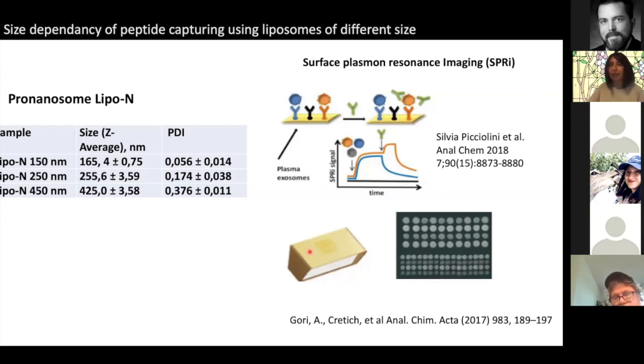And we are also lucky because previously we have worked with this group to develop a surface chemistry to immobilize peptides on these gold chips for SPR imaging. And this chemistry is exactly the same that we use for the silicon chips that I've shown you a few slides ago. So basically, we could directly compare the results that we have on the silicon chips and the NanoView instrument with what we had on the gold chips with the SPRI instrument, the surface plasmon resonance instrument.